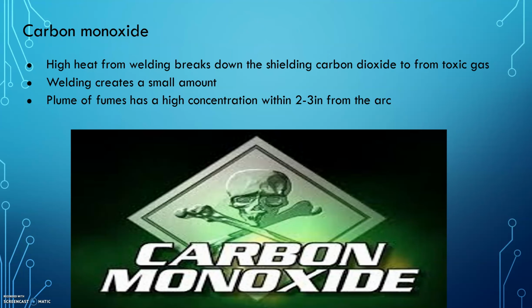When using carbon dioxide as a shielding gas, high arc energy can break the gas down into carbon monoxide. Not only is this toxic to your health, it affects welding by allowing small amounts of atmosphere into the weld area. This is why most wires designed to be used with CO2 have additional deoxidizers to counteract the gas loss. And for all you close welders out there, back your head out of the smoke to reduce exposure.